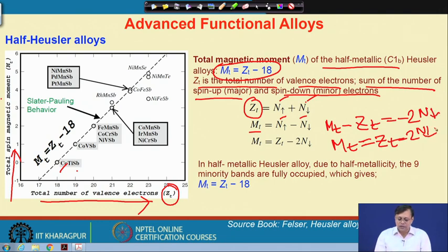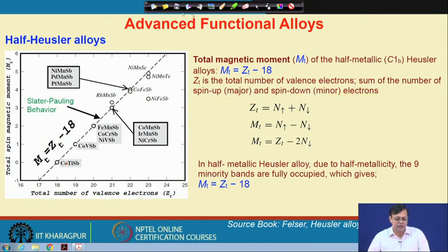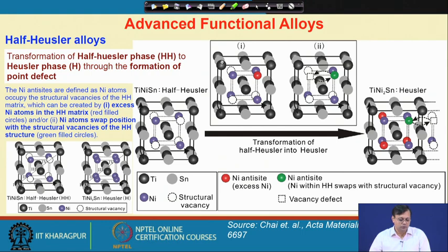Okay. So, for a half metallic alloy, due to the half metallicity, let us say 9 minority bands are occupied, and if I put 9 here, then the total is 18. So, this is the basic origin of these half Heusler alloys, and of how these spin magnetic moments are achieved due to the half metallicity in a compound.